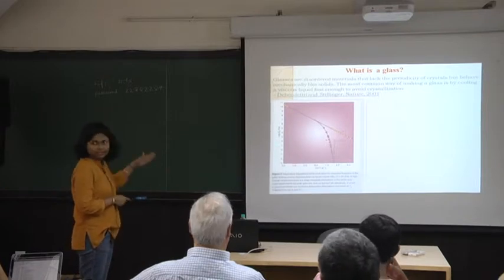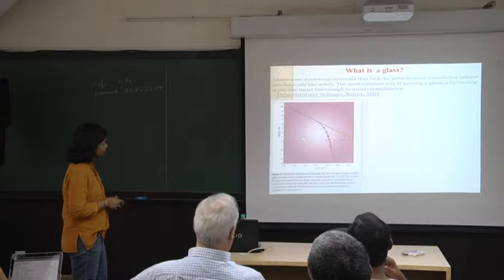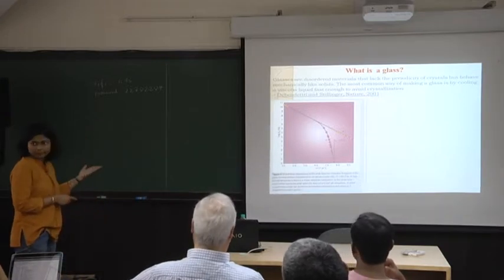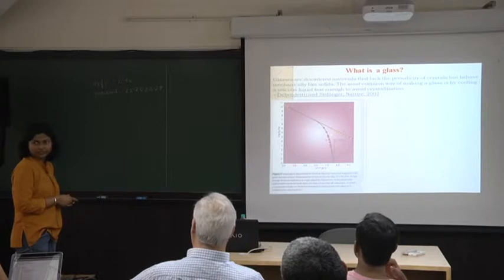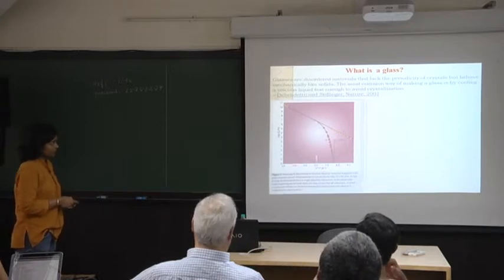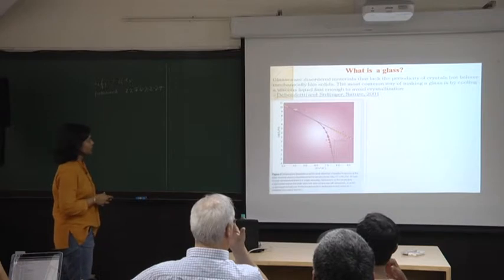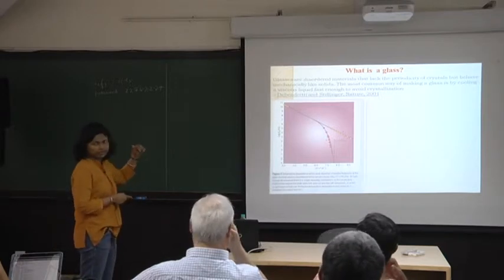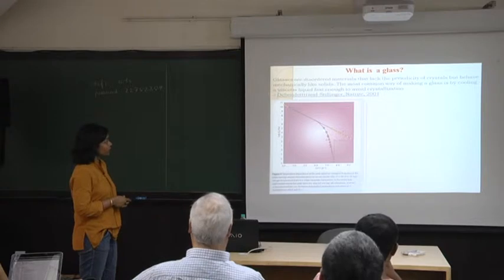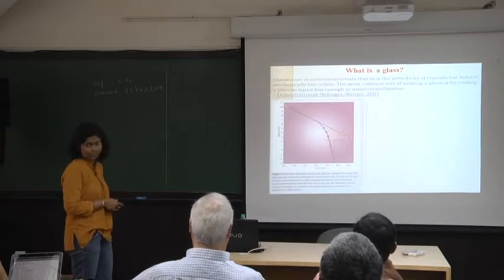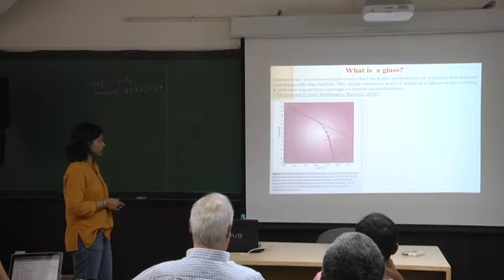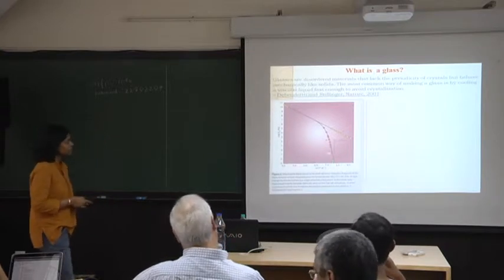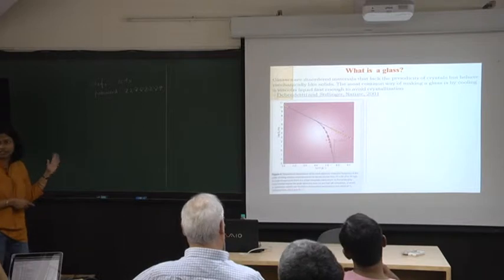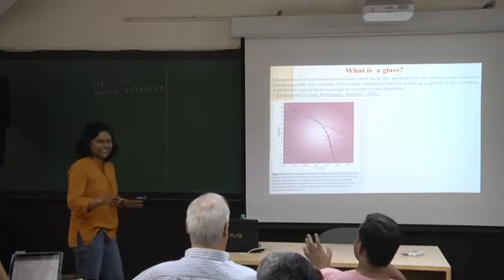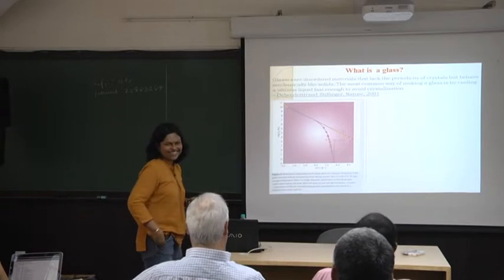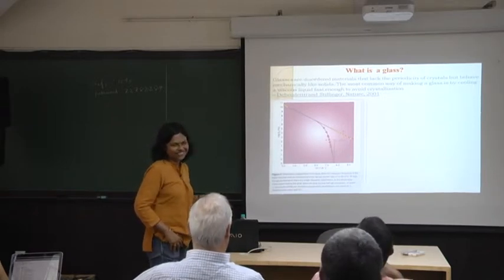So this is the peak dielectric frequency plotted versus the inverse of the temperature. You see that at the highest temperatures you get just one relaxation rate. Somewhere here, in the midst of the supercooled region, the frequencies split up into two. So now you suddenly have this emergence of a longer relaxation time, and this longer relaxation time, it goes to 0, this is a frequency, at a temperature that is the glass transition temperature. I know you have a problem with the extrapolation. Yes, I totally agree with that.